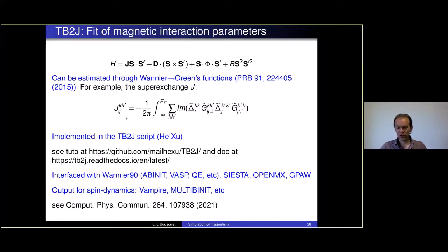When I say all of them, this means that you can extract the magnetic interaction at any distance and any order. And you can do it with a single point DFT energy. You just need one wave function for one magnetic ground state, for example, and out of that, you can extract all the magnetic interactions at all distances.